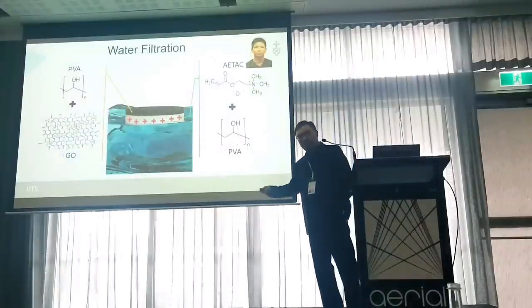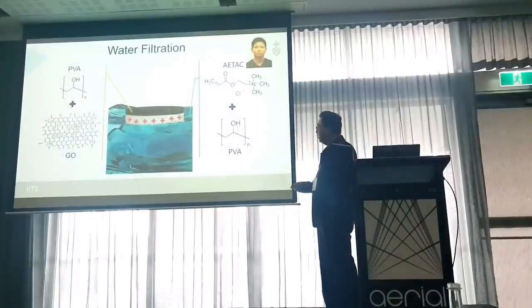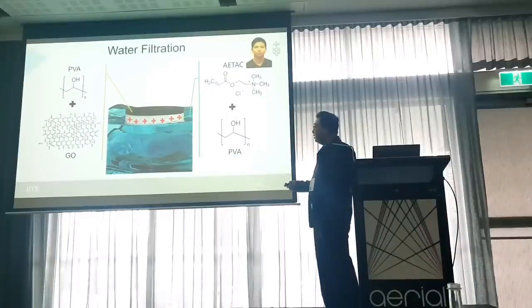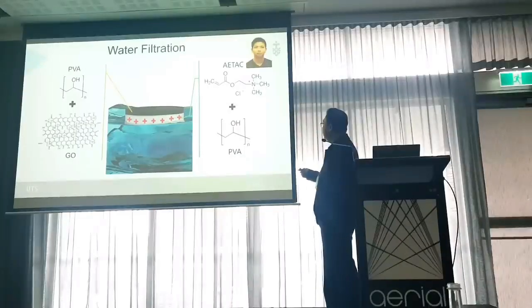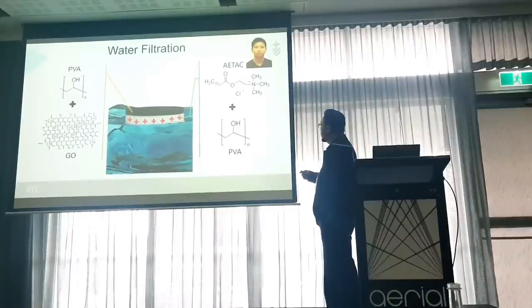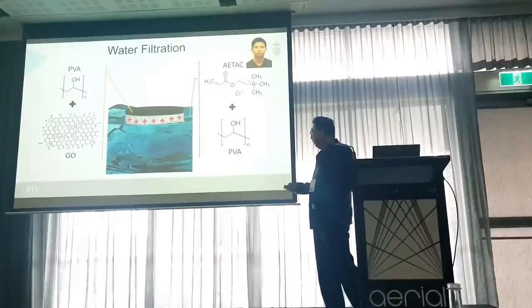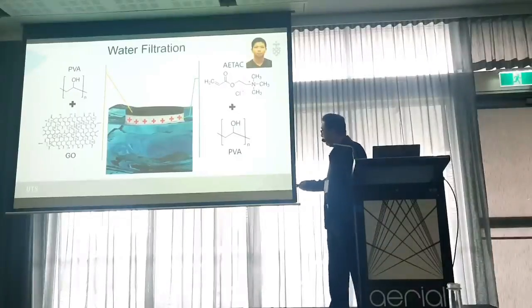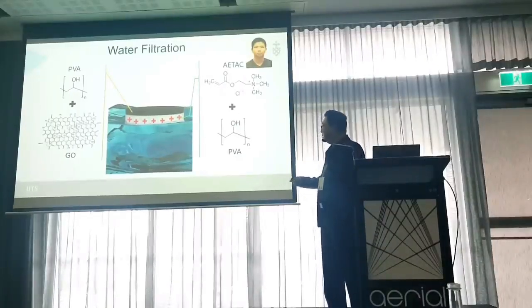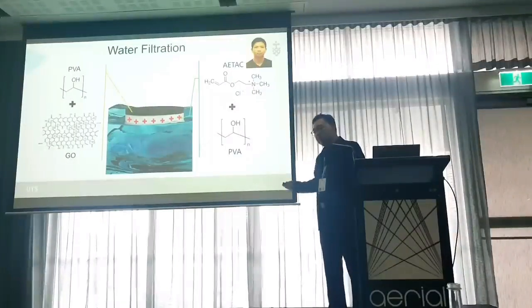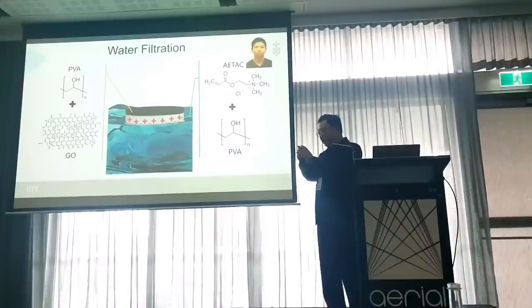Like our last study, we developed a novel dual-layer hydrogel system. The top layer is composed of PVA and graphene oxide, and the bottom layer is made from a polymer containing positively charged ammonium groups. We also added a certain amount of PVA because PVA can enhance the compatibility between these two layers, because different hydrogels have different swelling ratios. We don't want these two layers to just break apart.